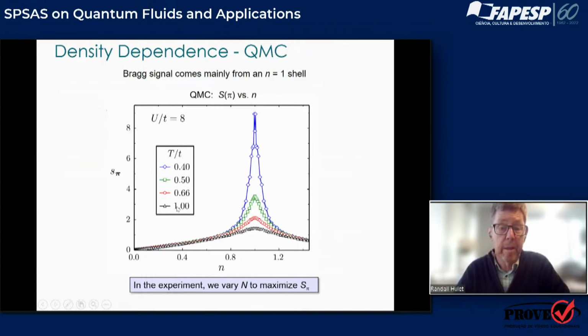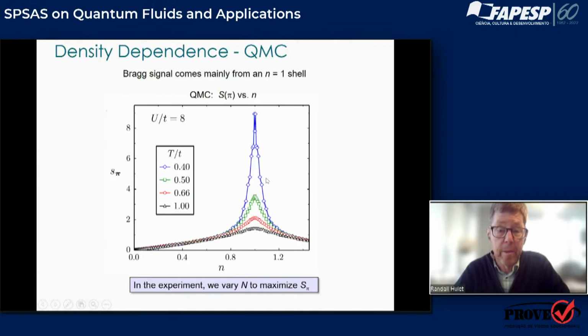So this is a calculation that shows the static structure factor as a function of density or doping. And so, of course, in our experiment, we vary the number of atoms to be near this half filling point where the correlations are maximum. And these different colors correspond to different temperatures. So you can see how sharply the correlations depend upon the temperature. This temperature range shown from blue to black is a factor of only 2.5 in temperature, but yet it's probably an order of magnitude in peak height.